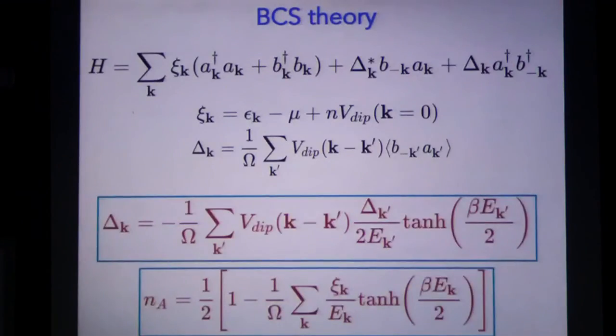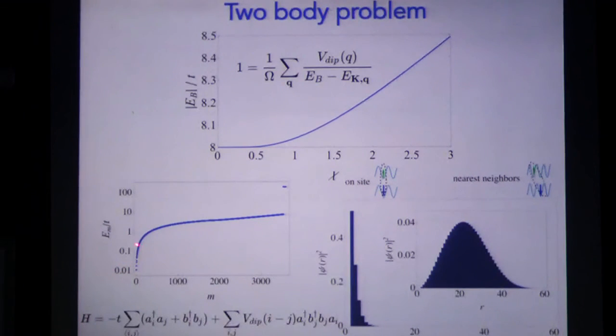So what you can see here is the exact solution, that is the exact diagonalization of the Schrödinger equation for the scattered states for a value of chi equal to 0.4, of course lower than 0.5, and this is the energy, and this is shifted. So this energy indeed is negative, but we shifted this energy just to show in a plot the whole energy spectrum. And what you can see here is a small set of configurations of energies associated to the highest possible energy. Why the highest possible energy?